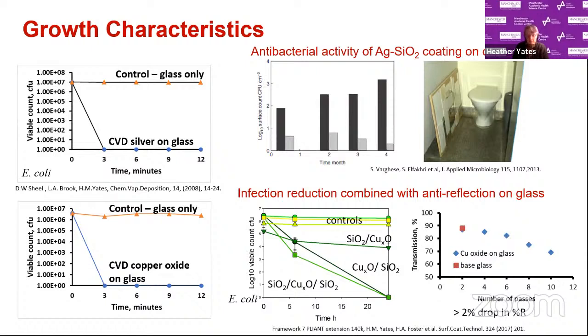You can see the three-layer mix worked best, reducing the bacterial count within at least 6 hours and maybe 24, that's when the tests were done. However, one of the problems is you want more copper in there to improve the antibacterial effect, but the more copper you add, as you can see from the light transmission, it massively reduces the amount of transmission of light. And for a touch screen, you do want to be able to see through it.